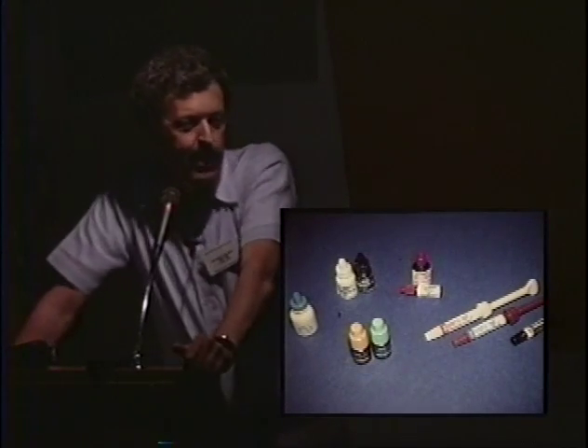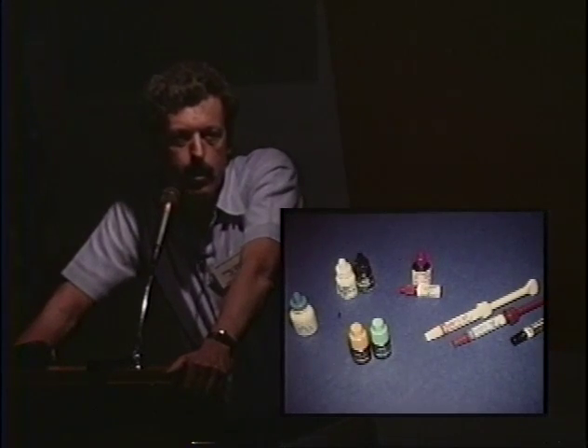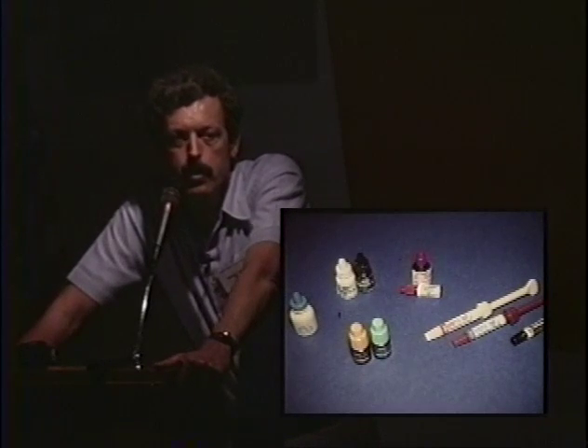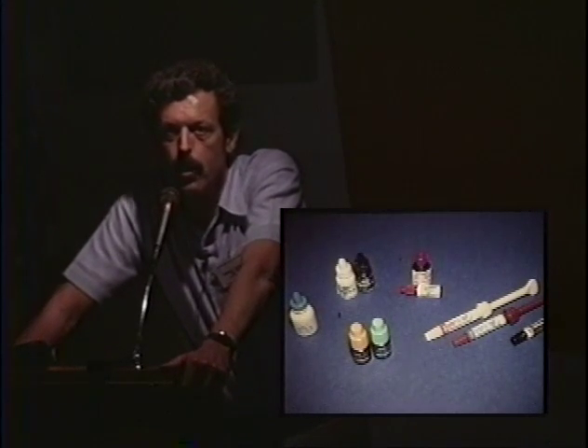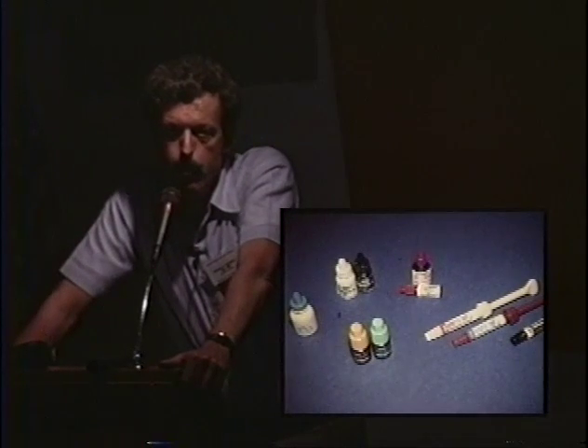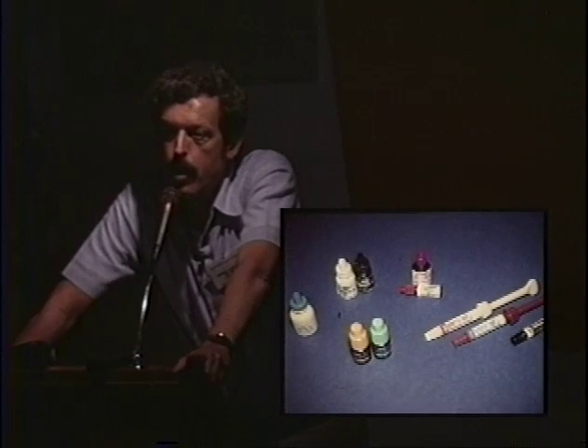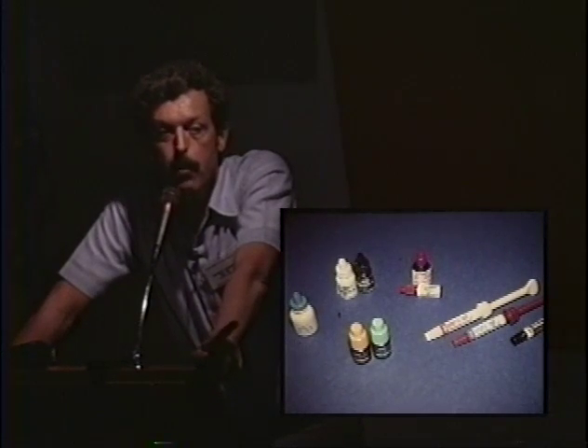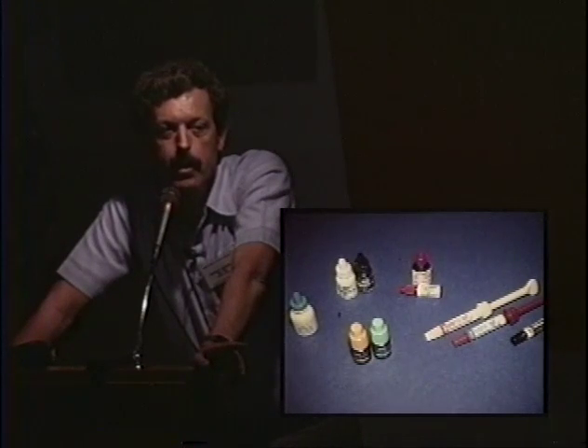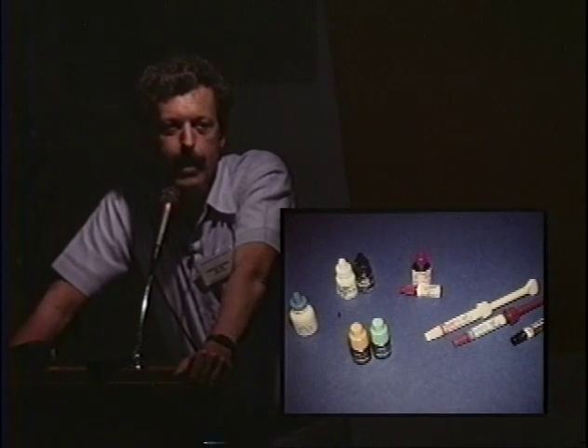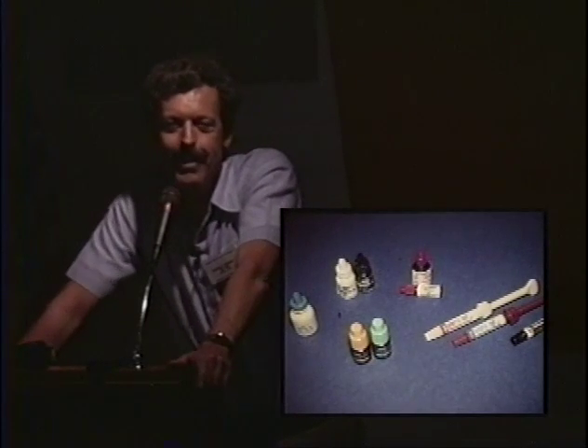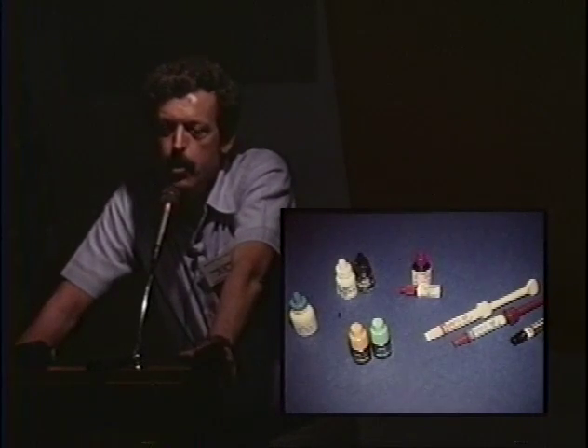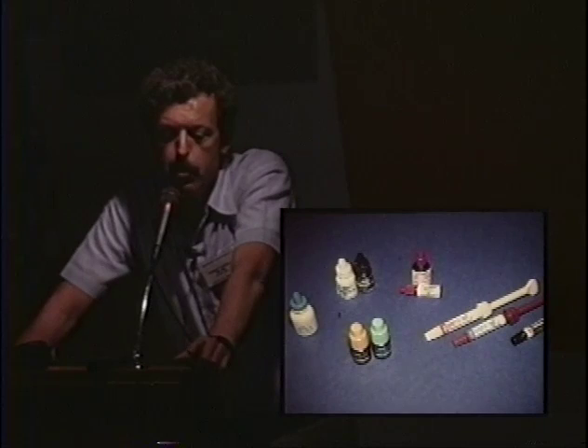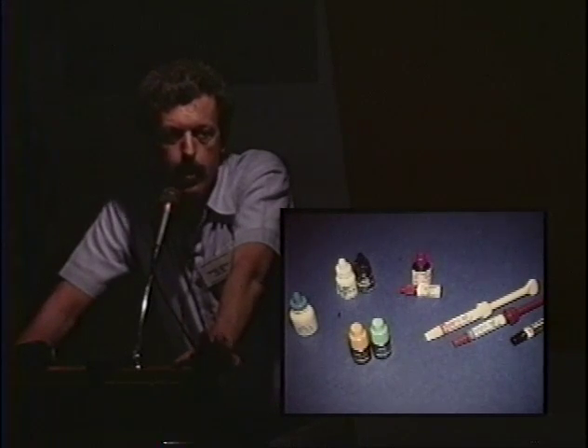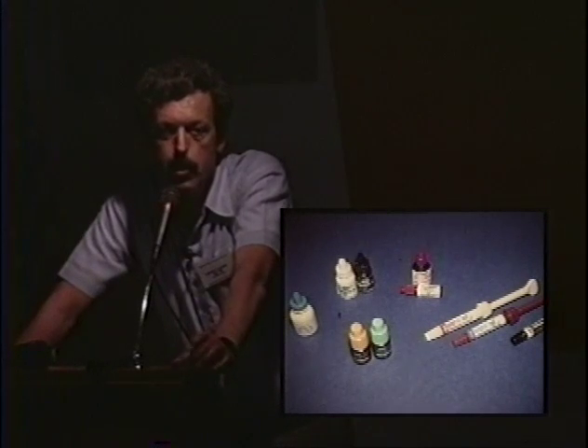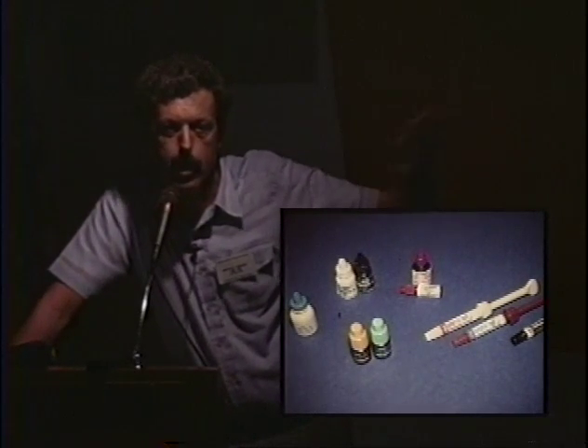Yes? Would you comment on the Meta system research that shows the hybrid dentin layer being more resistant to hydrochloric acid than enamel? Oh, it's true. The hybrid layer, not just with 4-META, however, the hybrid zone that's created between 4-META and decalcified dentin. And you know, by the way, with 4-META, they call the green stuff activator. That's bullshit. That's citric acid and ferric chloride. Citric acid, you know, like a decalcifier. Okay, so they're etching the dentin. All right, so you etch the dentin and you put in 4-META in methyl methacrylate with TBBO catalyst, tri-n-butylborane, and then you get a hybrid zone, and that resists the acid dissolution. But so does Photobond, so does All-Bond in the same analogous manner. The chemistry is just different.